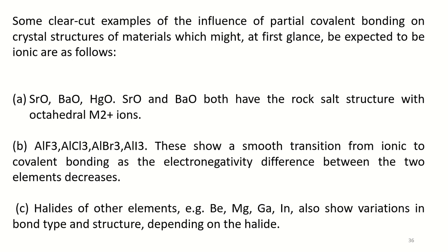If we talk about the size, based on size considerations alone, and if it were ionic in nature, mercury oxide should have the same structure. However, mercury is only 2-coordinate in HgO. Linear O-Hg-O segments occur and may be rationalized on the basis of sp hybridization of mercury.